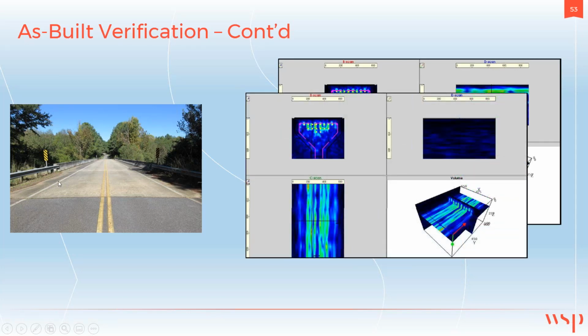Moving a little bit farther away from the test surface, we see 6 tendons in the second layer. So again, I'm moving this C scan, which is the plan view, away to the third level from the test surface. Now moving a little bit farther away, in the third level, we can identify 2 tendons. So compared to GPR, shear wave tomography gave us a much better picture, at least for this particular project.